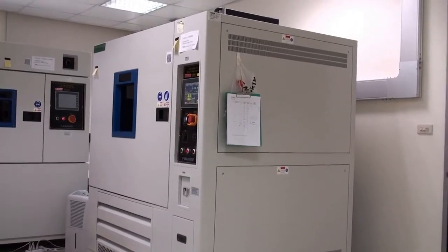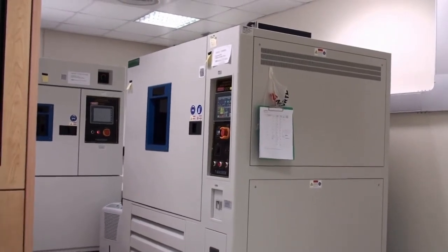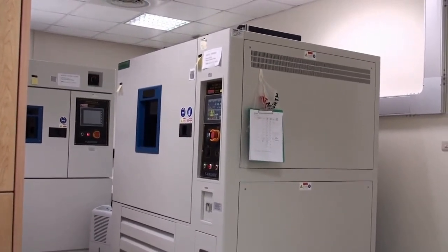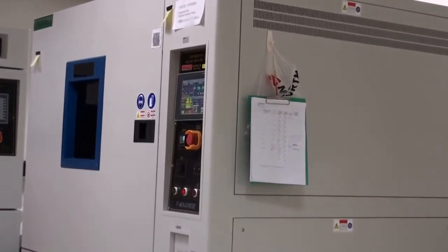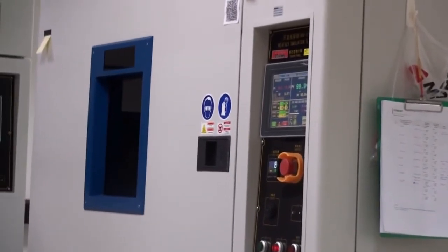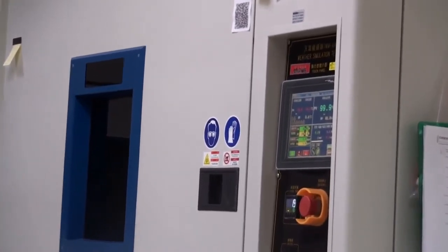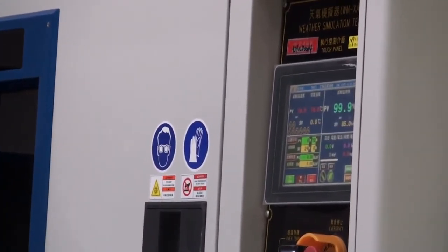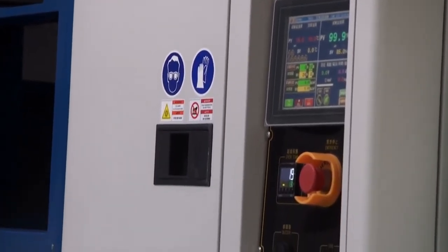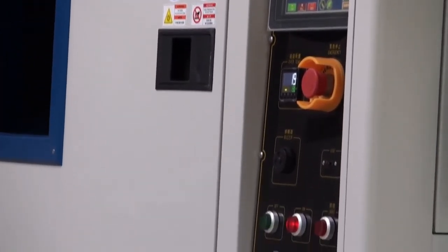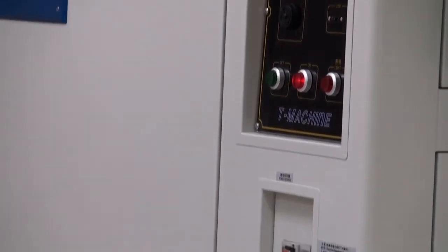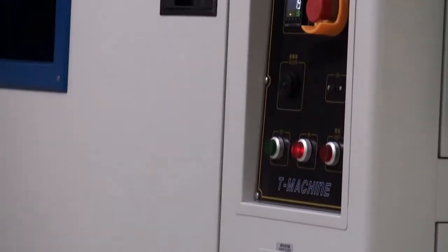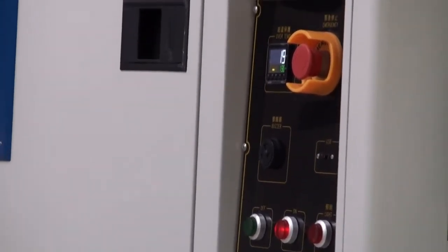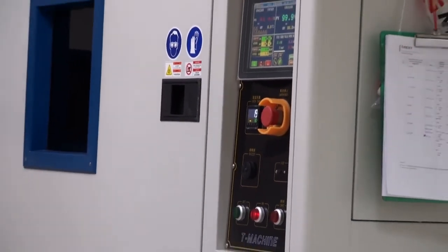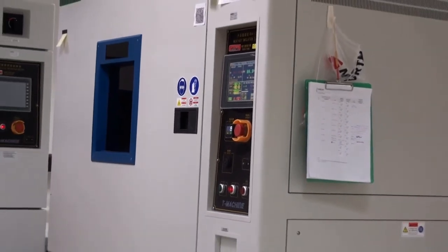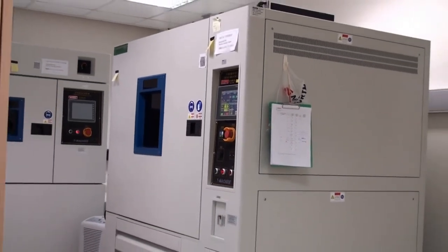This is the weather simulation tester. The model number is TMJ9707S. The light source in this one is 4000 watts and covers the whole solar light spectrum. The irradiation intensity in this chamber can go up to around 1400 watts per square meter, the chamber temperature ranges from minus 45 degrees C to 125 degrees C, and the humidity range is from 20% to around 98% relative humidity. This machine is designed to perform accelerated tests in order to check the reliability of the product.